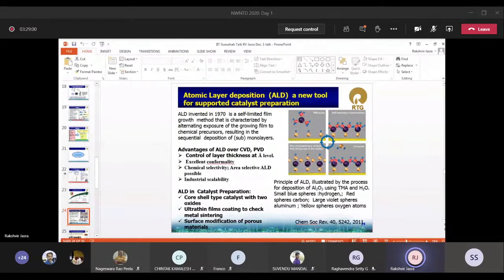And this is very cleverly done by the atomic layer deposition technique, which is used extensively by materials scientists. So we have put some metal oxide on it using this particular technique, and you can control how many atomic layers you want, like you can put 30 atomic layers, 40 atomic layers, whatever you want, so the diffusion of the reactants and products to platinum and tin is not affected, but the sintering is checked. This is what we did, and we were very, very successful in developing this catalyst.